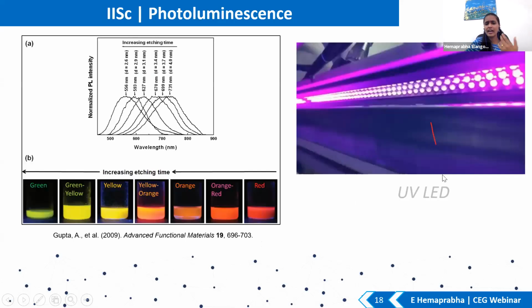So I had this kind of particles, and I was checking some optical properties, and we can see there is a phenomenon called photoluminescence. Suppose you send light through one material, it will take up that energy and then emit in a different way. For example, here you have a solution and they pass light from one direction, and these particles will emit at different wavelengths based on the size. For example, we have particles of 2.6 nanometer, 2.9 nanometer to 4 nanometer, and each emits light at a different wavelength. So you have a spectrum from green to red. You can have different colors just by tuning the size.